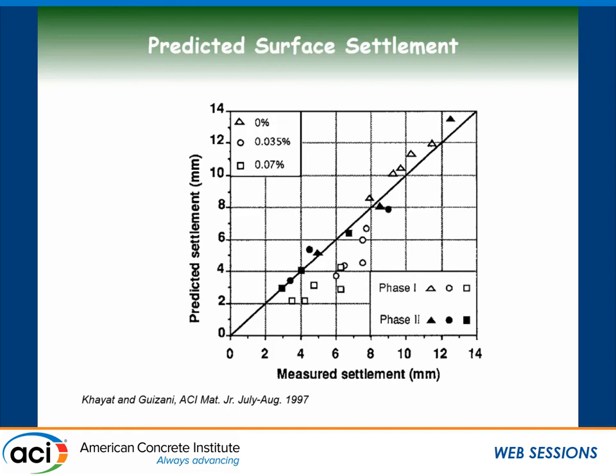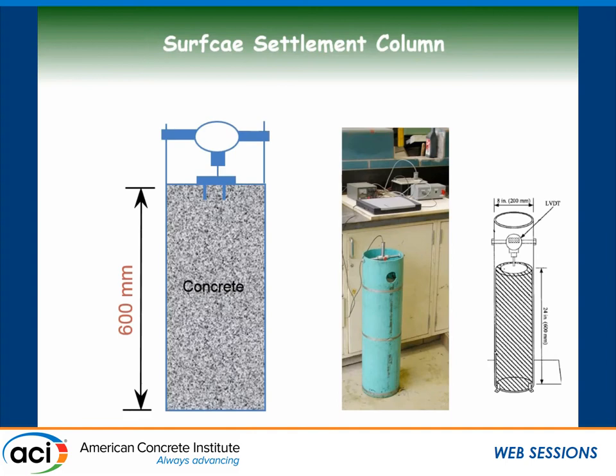So the message over here is static stability is more than surface settlement, it's more than bleeding, segregation. They're kind of interrelated physically. So after that study, we decided to pursue more surface settlement and see what's the implication on performance. We developed a test method that we've been using since, and it was proposed to AASHTO. And this is taking a sample of about 2 feet in height and casting that into a rigid PVC column. And at the top of the column, you put a very thin element that is anchored into the fresh concrete. And then using either a dial gauge or an LVDT, you monitor the settlement of the concrete until cessation of settlement.